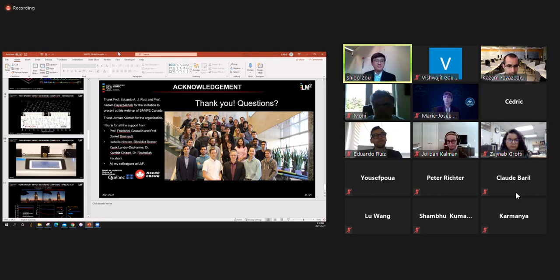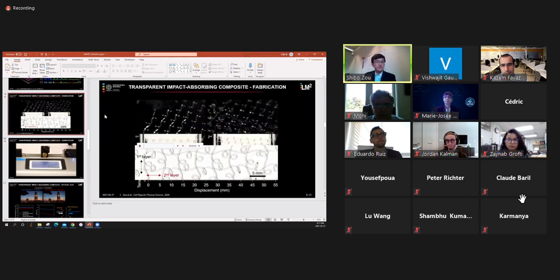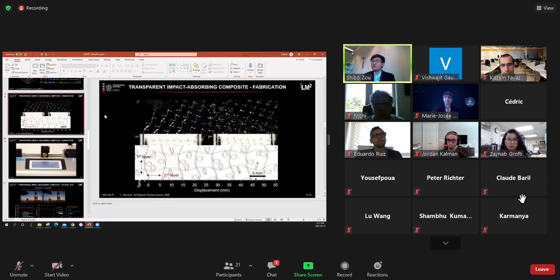Yes, thank you, Cedric, for the question. Yes, you're right. Normally, FDM 3D printing is quite slow if we want to create bulk engineered materials with complex structures. But in the methodology that we use here, we use the instability of the molten polymer thread to create this fiber fabric. Actually, the deposition process is quite quick because, in order to create this kind of complex structure, we don't manipulate the extruder to follow exactly the path of the fiber. We just ask the extruder to move along one straight line, and by manipulating the velocity difference between the extruding speed and the moving speed, we create this kind of structure by taking advantage of the instability of the molten polymer.